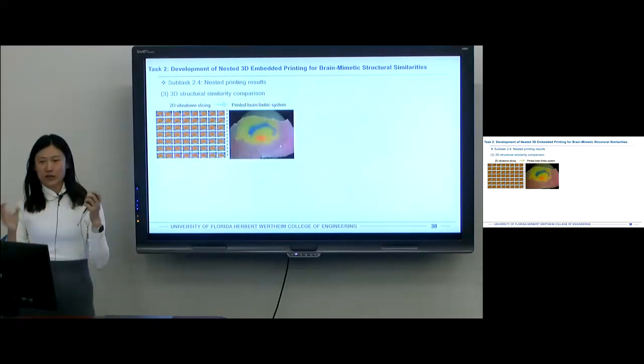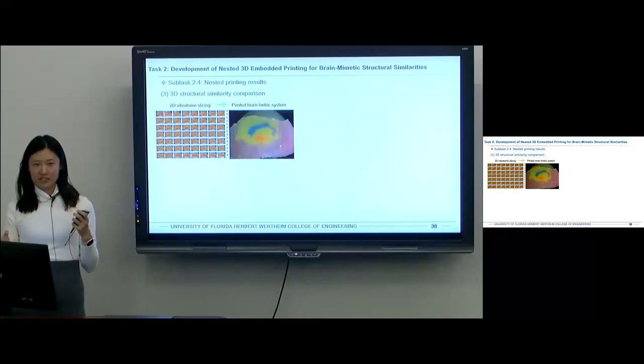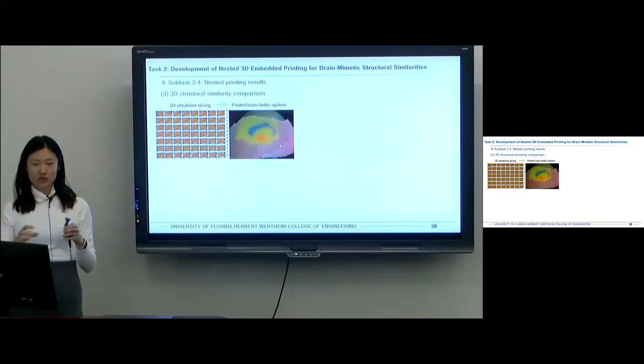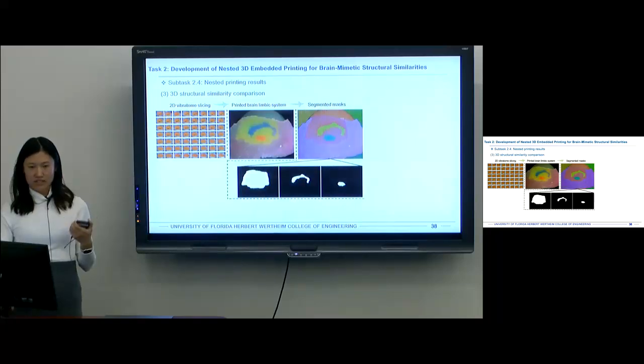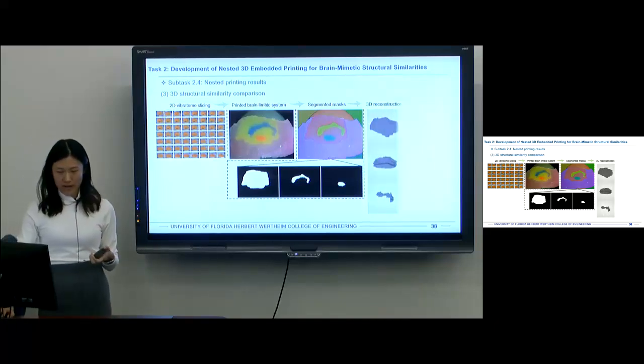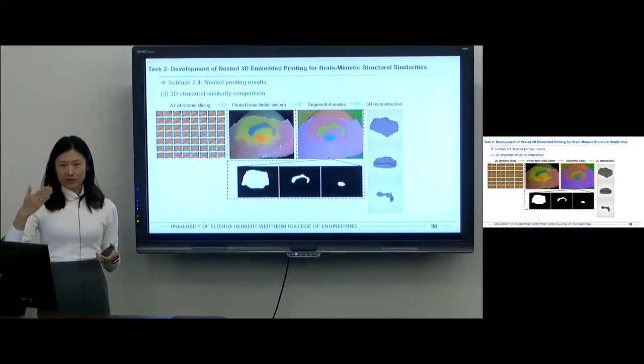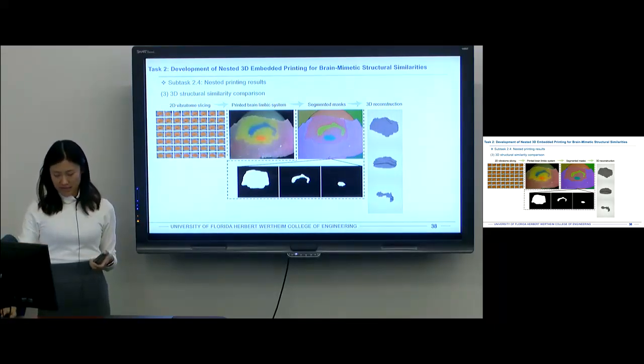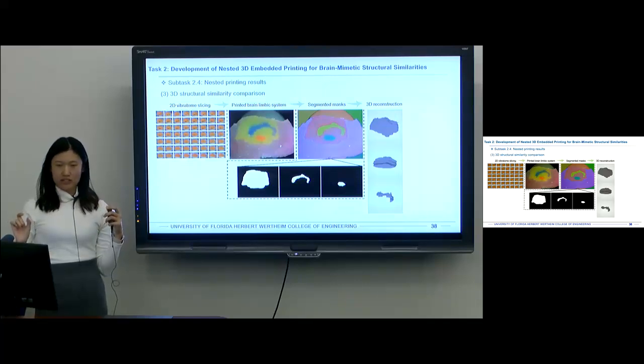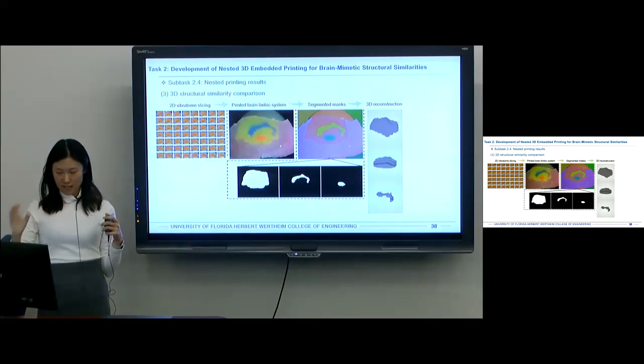So how do we evaluate the brain regions if we print them in 3D? It's also very difficult to use a CT scan to get the printing results because the densities are very similar. To visualize the printed 3D regions, we use a 3D structural similarity comparison by slicing them into 2D slices and then using image processing and segmentation.